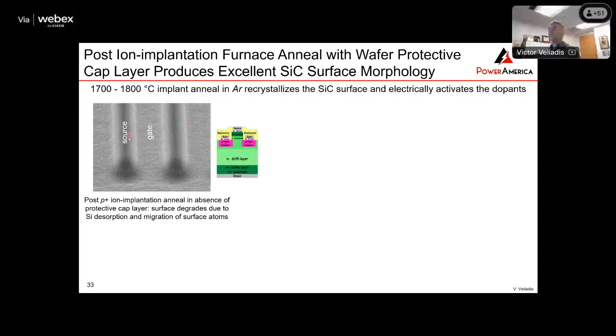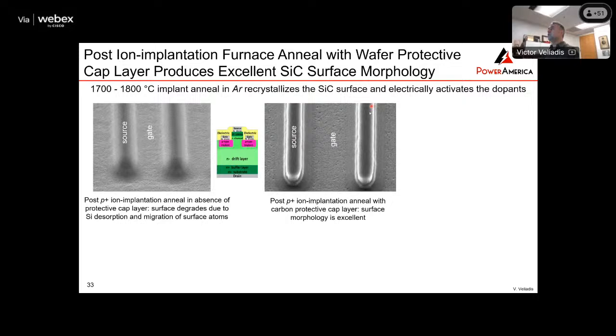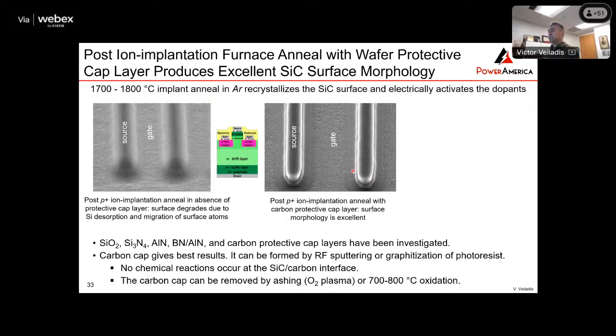And this is an anneal that was done without using a cap layer for the wafer. And you can see the quality is very, very poor. And here's the situation where you did use a cap layer and you get a very good surface. So the bottom line is there are different cap layers that you can use. What I have found works best is to use a carbon type of layer.